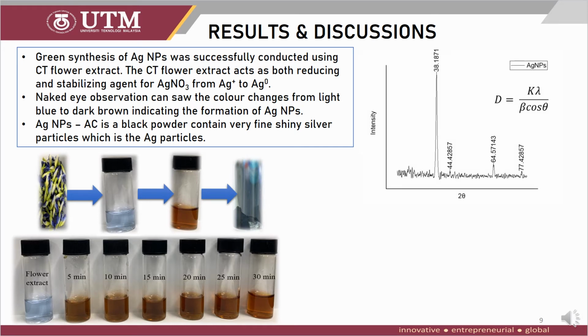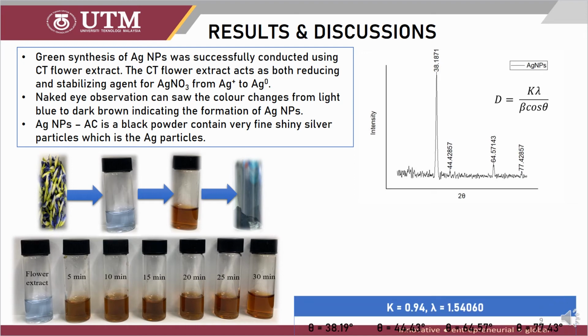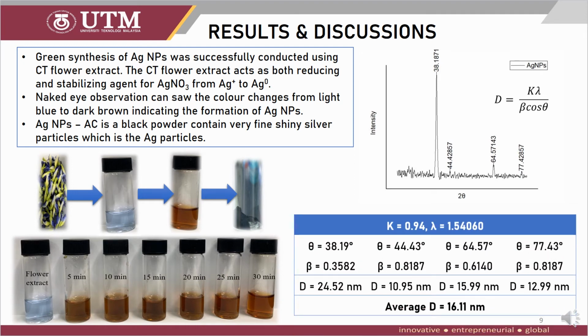And next, from the synthesis of silver nanoparticles, we can get the XRD analysis for the AgNPs. From this XRD analysis, we can see 4 peaks for the formation of silver nanoparticles. From these 4 peaks, we can use the Scherrer equation to get the average crystallite size of the silver nanoparticles, which is 16.11 nanometer.